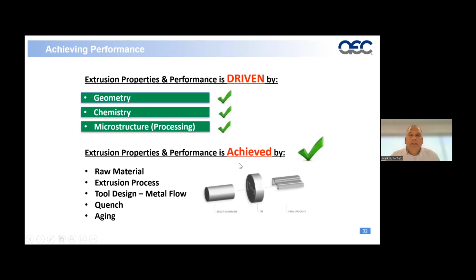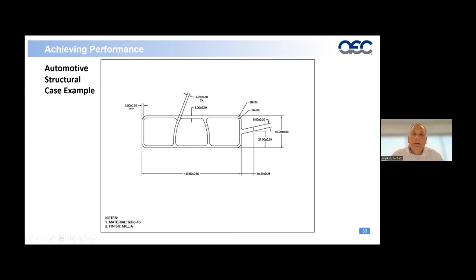So we talked a little bit about geometry, chemistry, and microstructure. We talked about the homogenization, the extrusion process, tool design, the metal flow that occurs in the tool, quench, and aging. So here's a very simple case study. This is an application of a bumper. Typically, this may be how we receive a print. Very straightforward cross-sectional dimensions, pretty basic information, material 6063 T6.